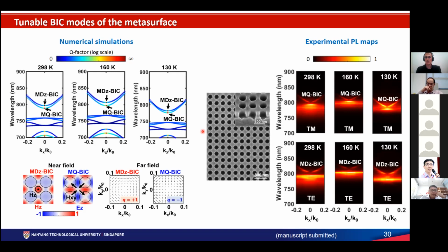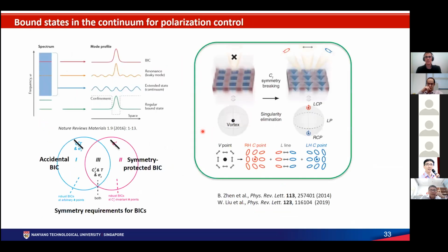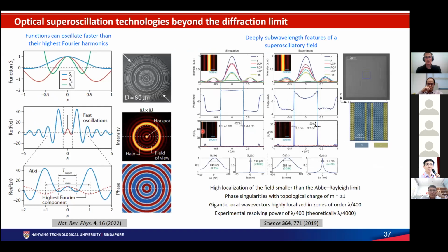The polarization, I think you can. We did, for example, in this case, it's a metasurface that has a different response depending on the polarization. For this experiment, they used all four polarizations to retrieve the images, so each polarization carries different information. It depends on the design. For example, this one you can illuminate with linear polarization, or you can think of illuminating with radial polarization. Every time you can adjust the design depending on the polarization you want to use. So it's a very open toolbox to play with, I would say.